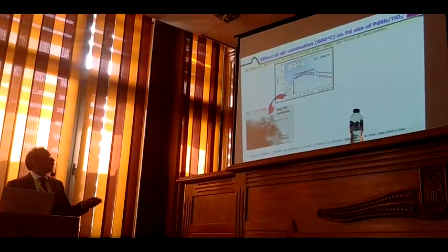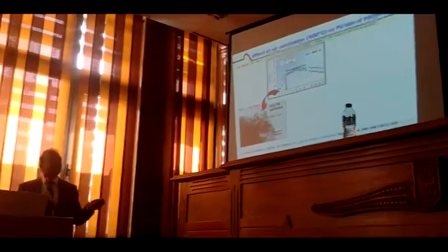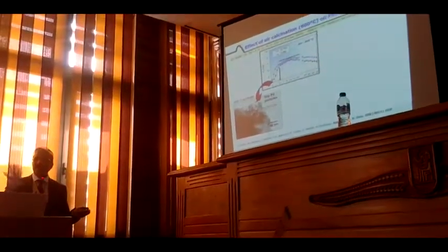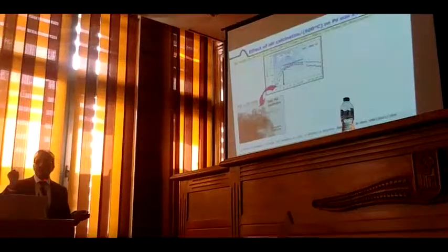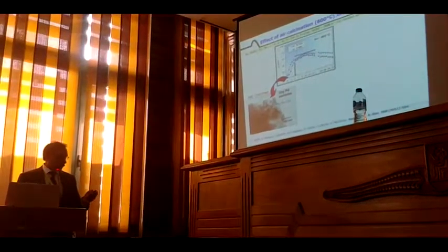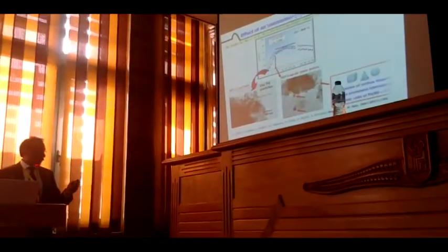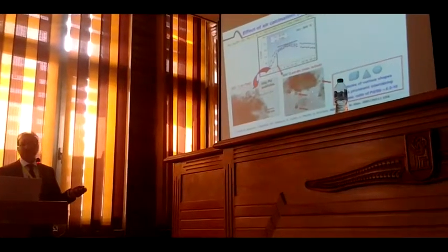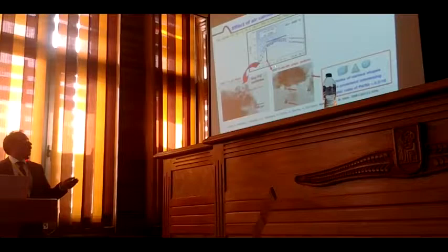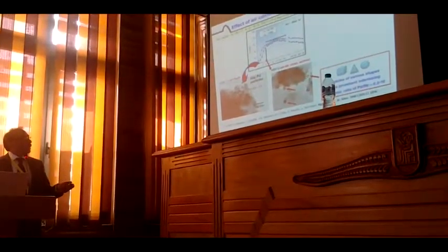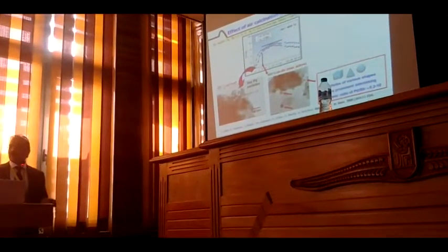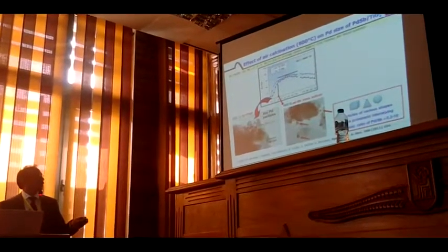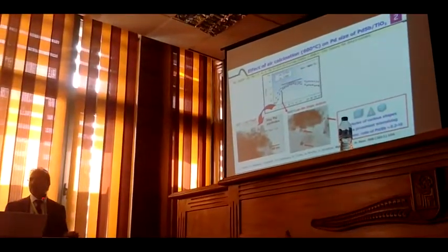The fresh one, even after calcination at 600 degrees C, you still have small palladium particles. The 600 degrees calcination has not made any growth in the palladium particle size. But when you reach the maximum activity, the particles have grown to 30 to 50 nanometers. And the particle shapes are different. You don't have uniform. We want to have uniform size, but you have cuboid, triangular, spherical, different shapes.